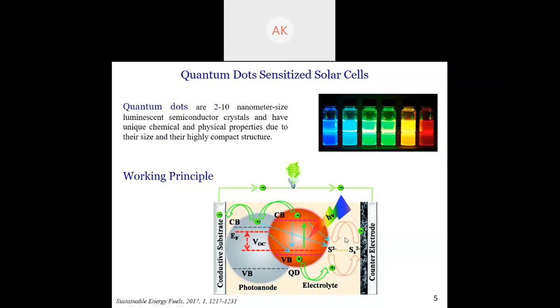Now, from the counter electrode, there are already, as I said, because of the quick scavenging of the hole from the quantum dot, oxidized and reduced species both present in the electrolyte. So these oxidized species capture the electron from the counter electrode and undergo reduction. Likewise, this sulfide electrolyte is regenerated and the entire cycle is completed. So the redox couple needs to undergo oxidation and reduction simultaneously. When it is undergoing oxidation by taking the electron from the valence band of the quantum dot, it is also undergoing reduction at the surface of the counter electrode.